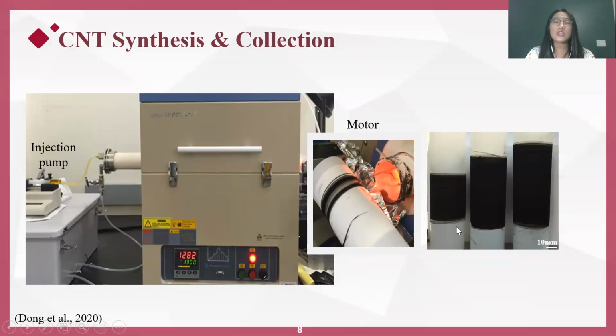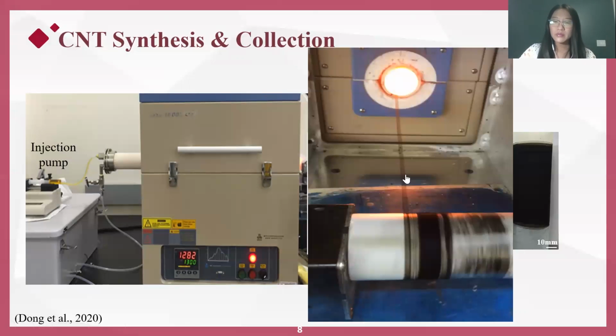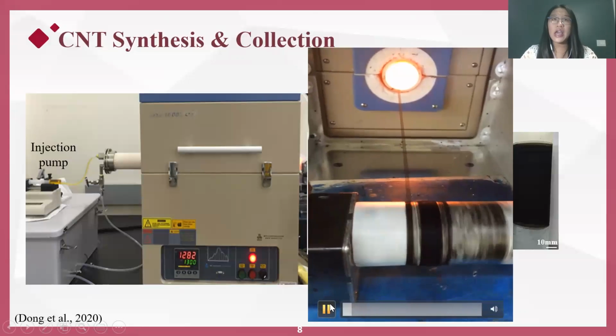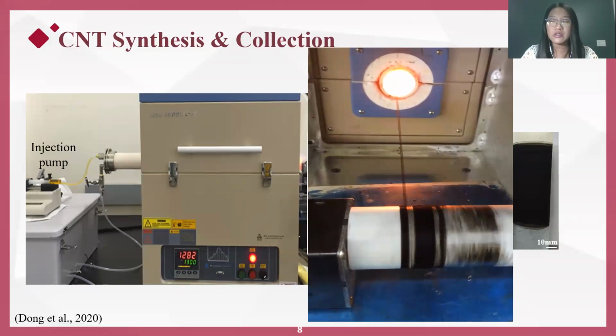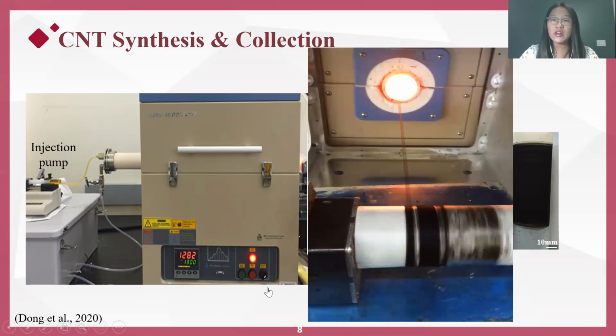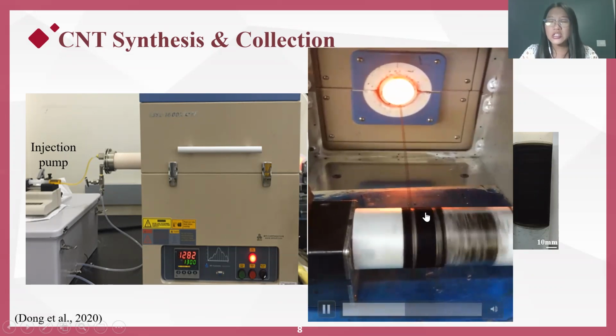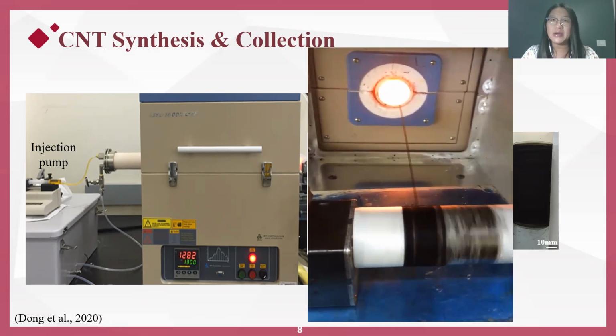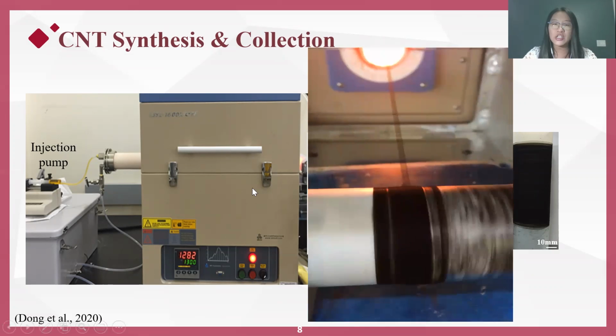Here in this slide, we are showing the in-house FCCVD setup for double-wall CNT synthesis. So as you can see, we have an injection pump on the left to control the catalyst feeding rate, a commercial alumina tube reactor, and on the other side, a rotating mandrel covered with Teflon sheet to serve as a sample holder. Here is a video showing the aerogel-like CNT socks being continuously collected. The stretching force from the rotation induces a mechanical stretch on the CNT bundles and slightly aligns them. And we'll talk more about this in the later sections.